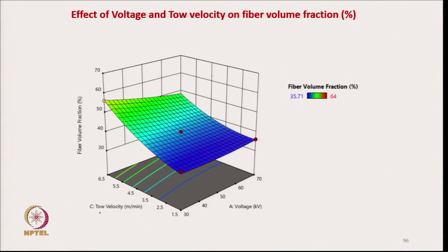So, if we see here the tow velocity, with the increase in tow velocity the fiber volume fraction increases, which means, as we have seen earlier, with the increase in tow velocity the resin fraction reduces. It is the same: with the increase in tow velocity the fiber volume fraction increases, that means there is a reduction in resin content. Okay. But the advantage of this response surface is that within this experimental zone we can get the trend of the parameter at different levels, like at